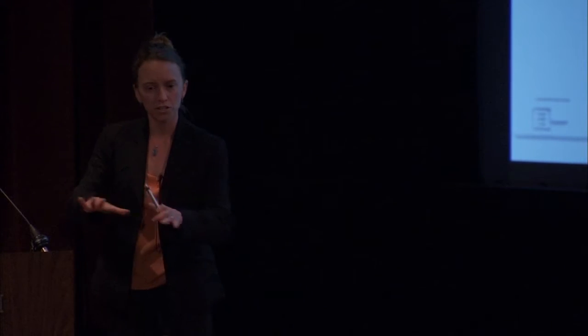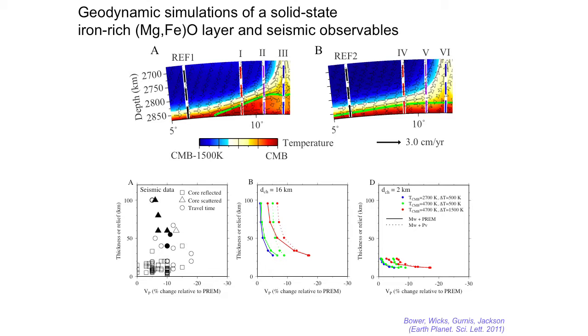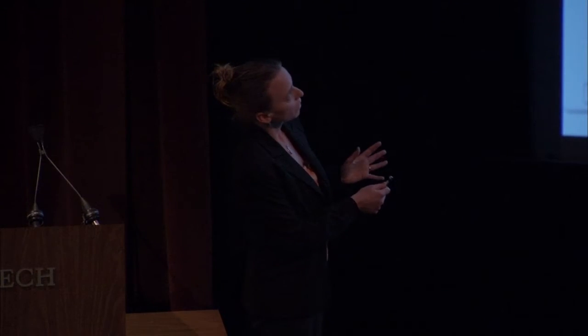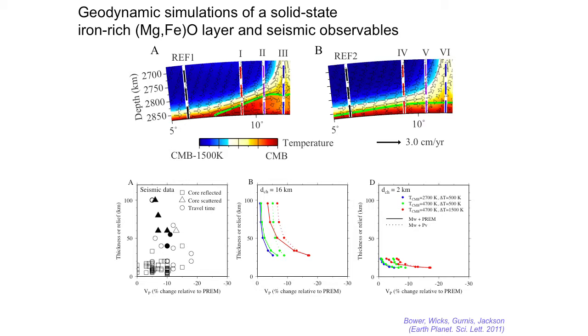But is it dynamically stable? Recall the melt example where it's been difficult to contain the melt, or that it just pools around and forms a ubiquitous, very thin layer, which can't really be explained from seismic observations. So PhD student Dan Bauer did geodynamic simulations including this iron-rich oxide as a distinct chemical layer. And with different proportions of that oxide, we get either bulbous-like or teepee-like shapes with perhaps some entrainment into the mantle, which means some of it escapes.